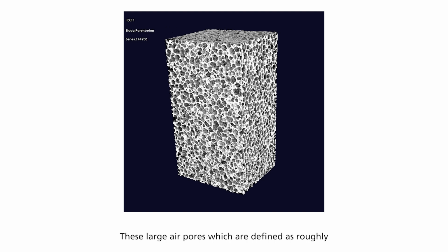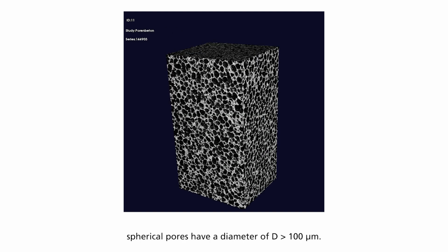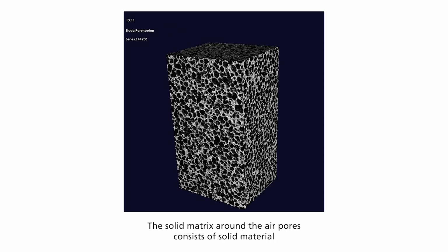These large air pores, which are defined as roughly spherical pores, have a diameter of about 100 microns, and the solid matrix around these air pores consists of solid material and mostly irregular pores, which are referred to as micropores. In other words, the solid matrix contains another part of the total porosity in its microstructure, which makes up from 13 to 41% of the total volume.